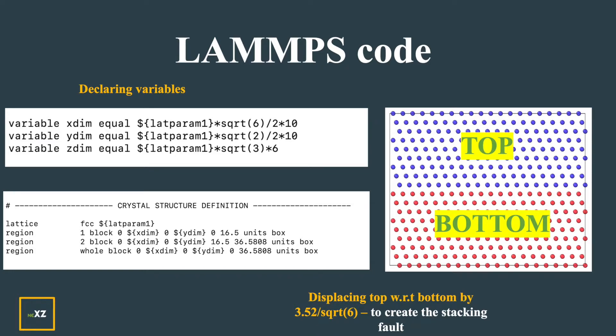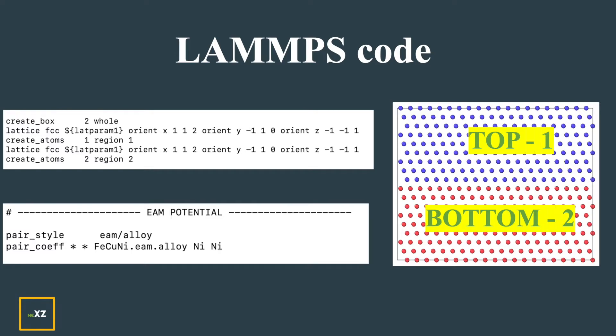We are displacing the top with respect to the bottom by a/sqrt(6) to create the stacking fault. The top is region 1, so first I create the box with the whole region, then I give the lattice structure for the top region with the orientation shown before. I create atoms type 1 for region 1 and atoms type 2 for region 2 — different colors so we can see the difference. I use the EAM potential with pair coefficient nickel-nickel so both atom types interact as nickel-nickel.